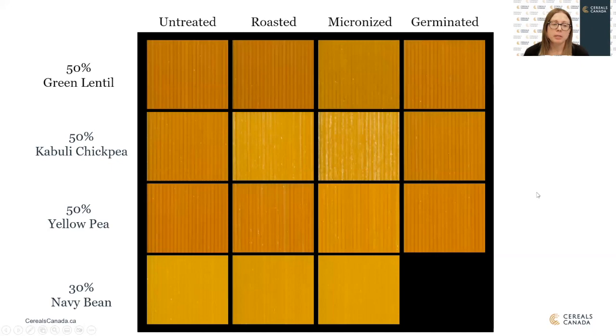So again, we used them in spaghetti as well. The significant change in color for the roasted and micronized samples for the majority of the pulse types compared to untreated was really a surprise. Typically when you heat treat a flour, you're expecting it to produce a darker or more red color product, and that really wasn't the case here when we looked at the dried spaghetti color. You can really see it in the chickpea pasta. The micronized samples